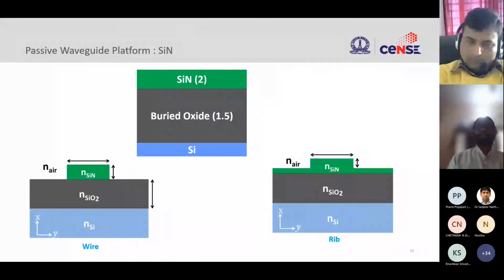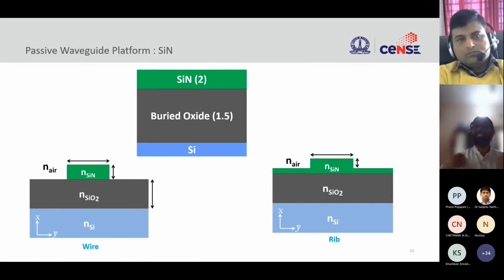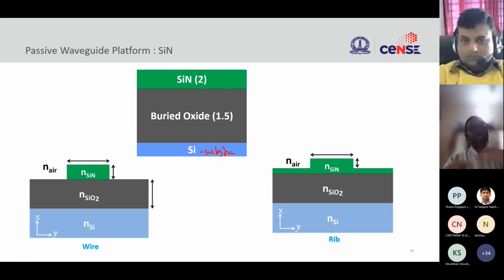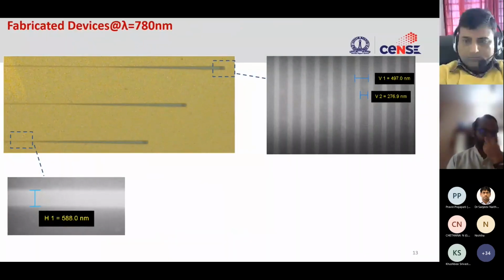And then using these thin films that we developed, we thought, why don't we make waveguides out of it, right? Let's make a waveguide, put the light through, and measure those waveguides to see whether light propagates through them. So we start off with such a stack, where we take a silicon substrate and deposit an oxide layer on top, and then on top of that oxide layer we deposit silicon nitride, and then we make the two types of waveguides that I discussed already. Then you can measure the propagation loss.